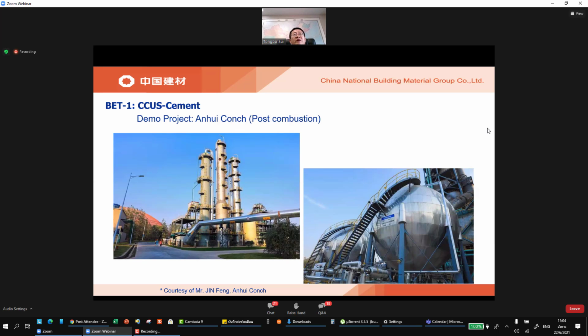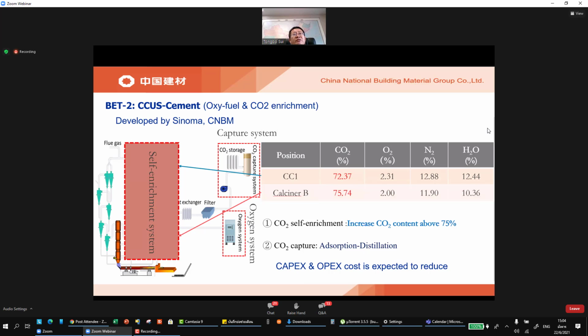The second CCUS: in China, Sinoma also developed the oxy-fuel and CO2 enrichment process for CCUS technology. With this oxy-fuel process, we expect to concentrate CO2 from normally 20-30% up to 70 to 75%. So with the enrichment of CO2, we expect to considerably reduce the capex and the opex of the CCUS system.